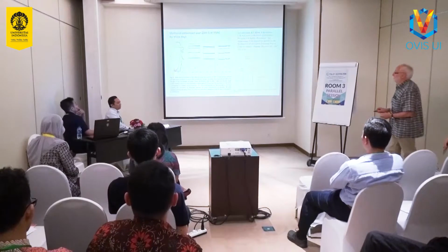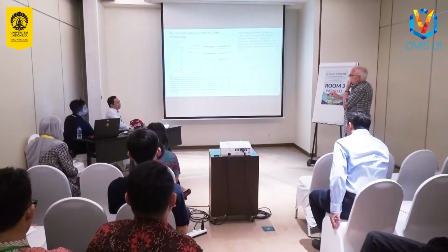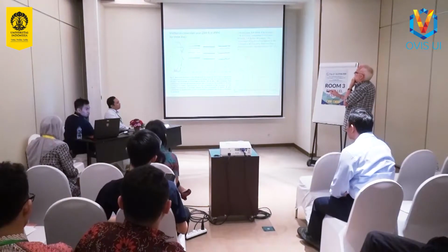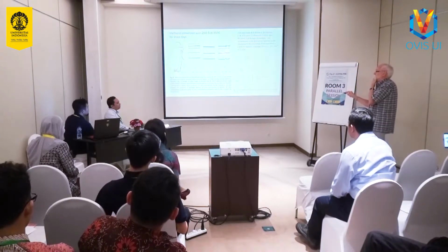If we go to 350 degrees C, we start seeing steady state production of gasoline in the reactor. This is mass spec traces, which are probably quite hard for you to see. What I'd like you to notice though is that initially, so this is the first few minutes of reaction. This is day 1, day 2, day 3. Here we've got a steady state. Mass 55 is butene, mass 91 is aromatics, mass 41 is propene. We're making steady state production here of gasoline range hydrocarbons, light olefins and aromatics.